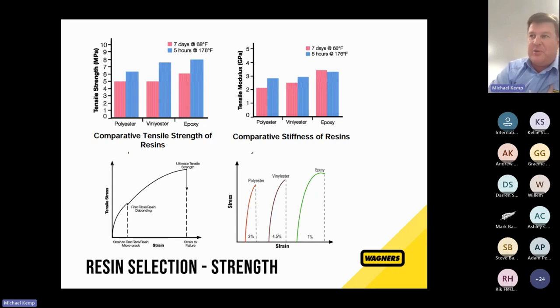With a polyester resin, observationally in my 20-year history at Composites, and of course doing the maths, we'll see that this first cracking will happen at a fairly low number. It might happen at 50% of the ultimate capacity of a sample. With a vinylester resin, we're seeing that much higher. Typically with our products, we're starting to hear that cracking at upwards of 90% of its final capacity. So what does that mean? If we move this line from a fairly low area on this curve up to a higher area, it means that we're in our operating range of the product and not getting that cracking. So we're going to see it last for a longer life.